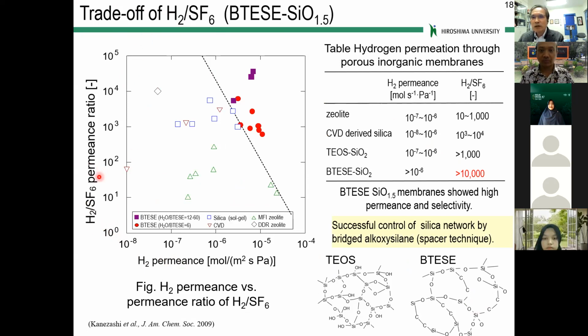The selectivity, the permeance ratio, is plotted against the hydrogen permeance. Of course, higher permeance and higher selectivity is better for good membranes. Here we have some plots collected from the literature together with our membranes: conventional silica as squares, CVD as triangles, also zeolite membranes as triangles and diamonds. You can see our BTESE-derived membranes show very high permeance, higher than 10^-5, and also high selectivity of more than 1,000. So we would like to conclude that we successfully controlled the silica network by using bridged alkoxysilane as a spacer technique.